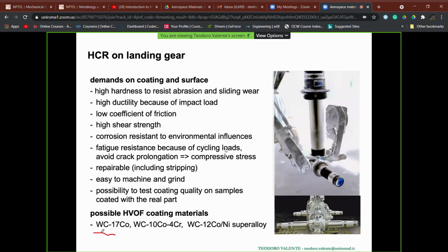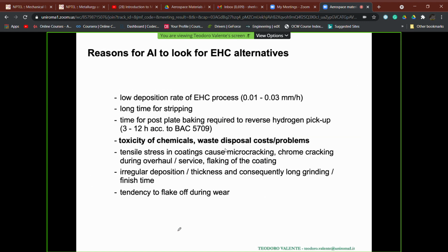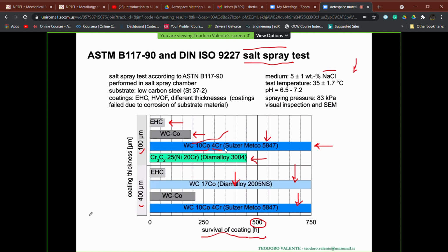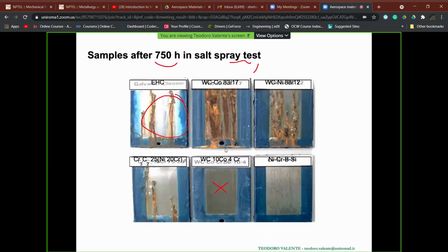Another example, and if you see here, the materials which are considered to be used are those I have shown to you. The best performance, for example for corrosion resistance, is the tungsten carbide 10 cobalt or the tungsten carbide 10 cobalt 4 chromium, which are, as we have seen here, the best performing materials among the fabricated coatings to contrast corrosion due to the presence of salt in the environment, evaluated on a lab scale with a salt spray test.